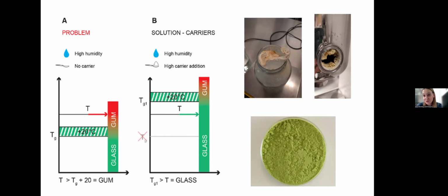So what are the solutions normally in the industry, and what is our solution as a team working at my department? To understand a bit more about how and when we observe the stickiness problem, I would like to present you this short graph figure where you can see that generally, when we do not have any carrier in the powders and we have, let's say, ambient or even high humidity of drying air, we observe the stickiness in the zone over 20 Celsius degrees above the glass transition temperature. So if the material reaches this zone over 20 Celsius degrees over the glass transition temperature, we will observe the problems.